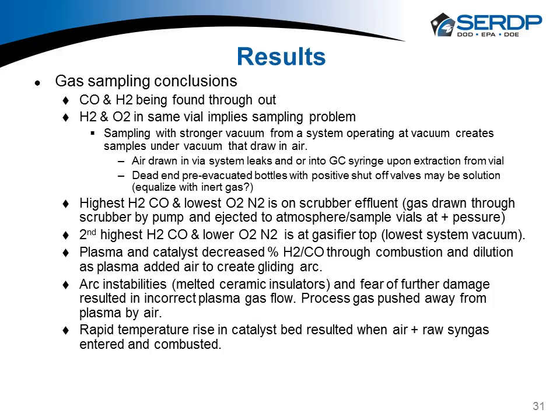And there's other things we could do about dead end pre-evacuated volume vials or bottles, and somehow equalizing them with inert gas prior to the GC operation. What kind of confirms this sampling issue is that the highest hydrogen and carbon monoxide and the lowest oxygen and nitrogen is on the scrubber effluent. That's the gas that's drawn through the scrubber by the pump and ejected to atmosphere, or in this case pumped into the vials at positive pressure, or at least near atmospheric pressure. So there we didn't have what I just described, vials that are existing at a vacuum.